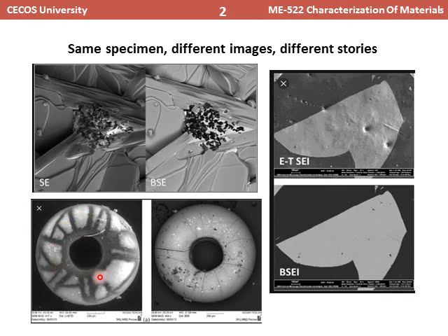So in the secondary electron image of the donut shape, the islands of lump masses are easily visible on the donut surface, whereas backscattered electron can show that these cracks that are visible on the secondary electron are much more in depth, because as you know, in backscattered electron the electrons penetrate much deeper inside the surface of the specimen, and then they are bounced back or deflected back.